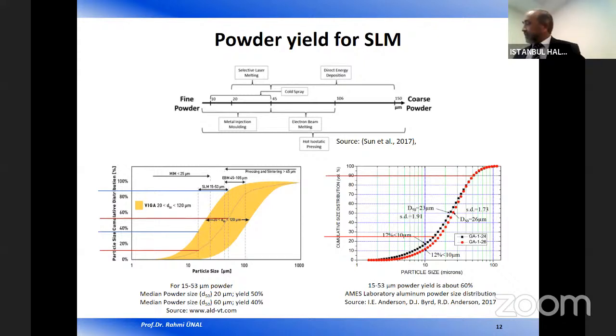The left figure is from ALD, and the right figure is from a laboratory in the USA. It is about aluminum powder size distribution. It has a similar size distribution for 15 to 53 micrometer powder. Yield is about 60%. So we can say that the yield for this powder size range can be from 40 to 50%. It increases the costs.